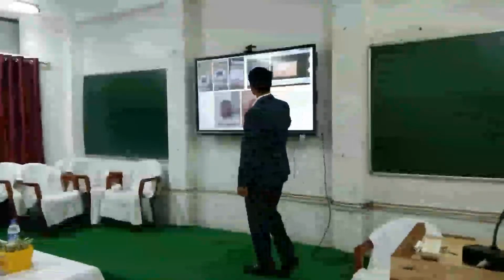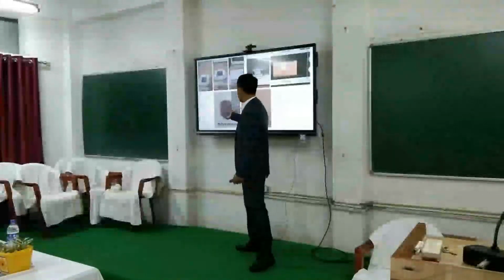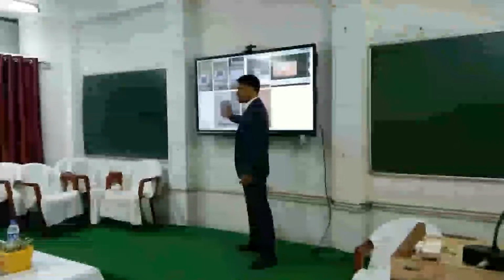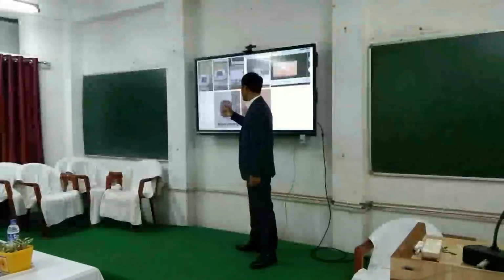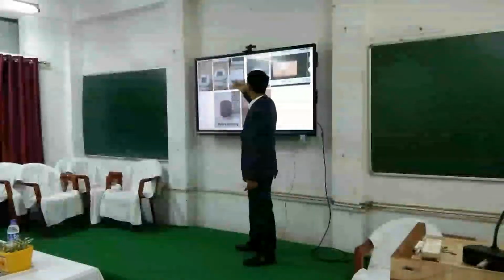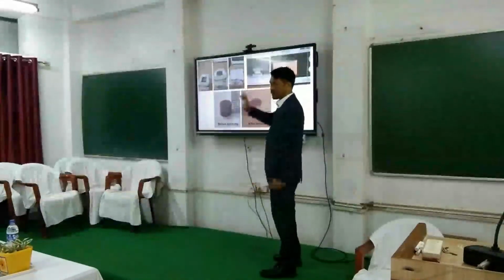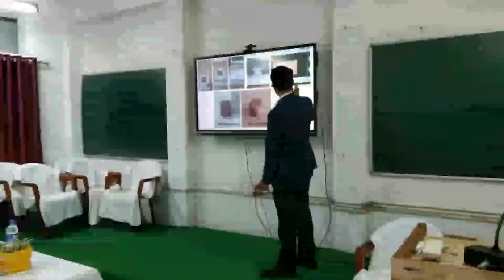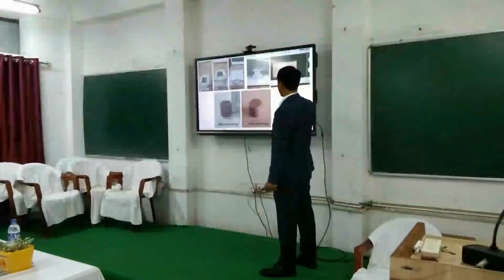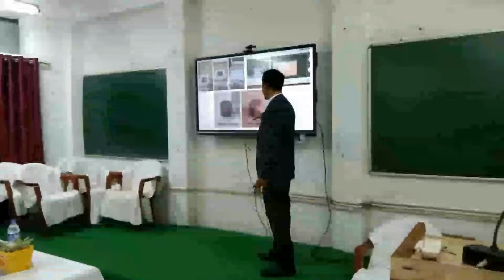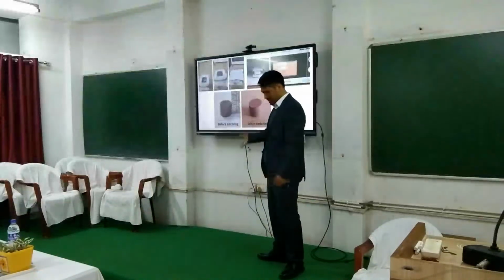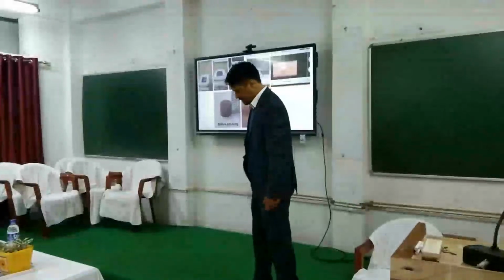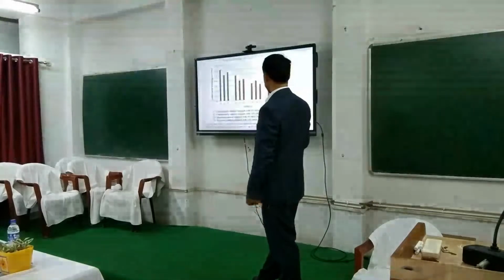So we use pure copper here, and these green samples, which are before sintering, we have compressed and made into small cylindrical samples, and then we undergo microwave heat treatment. This is a simple normal heating oven, now converted to a furnace, and after sintering we can achieve this sintering of copper. This is at around 1000 degrees Celsius.